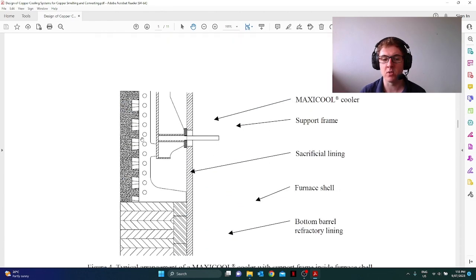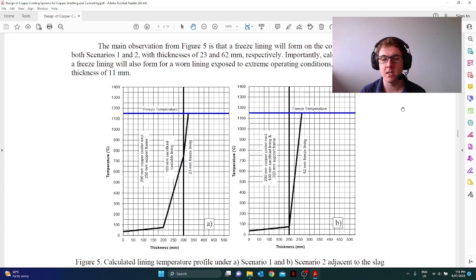These ones have copper elements, and you can see that the hot face temperature of the castable is below the temperature of the bath, and with the hot face being below it, you're going to freeze material on and form a freeze lining. As that castable changes, at the start of the campaign you may knock some castable off, but that freeze lining is always there. So theoretically, you should not be eroding away your copper coolers.